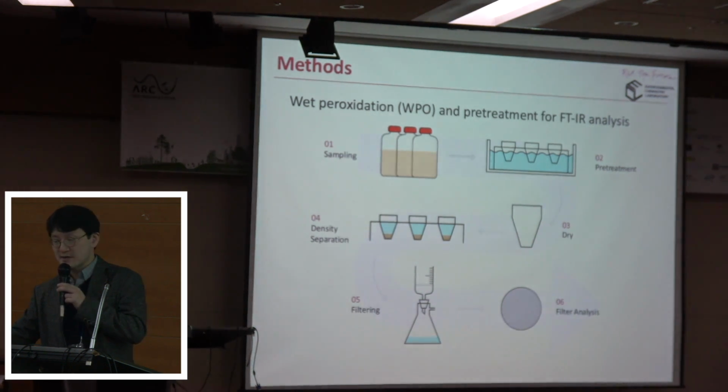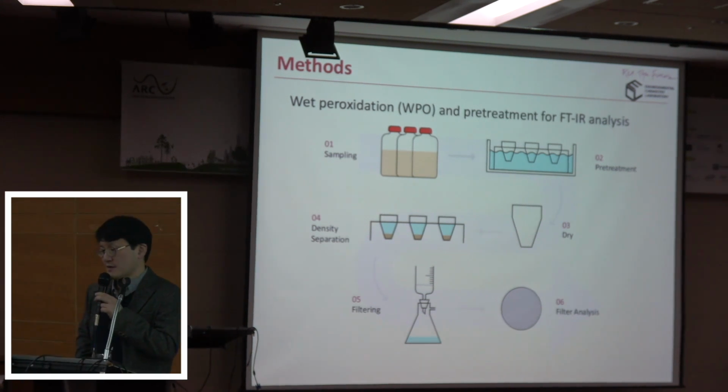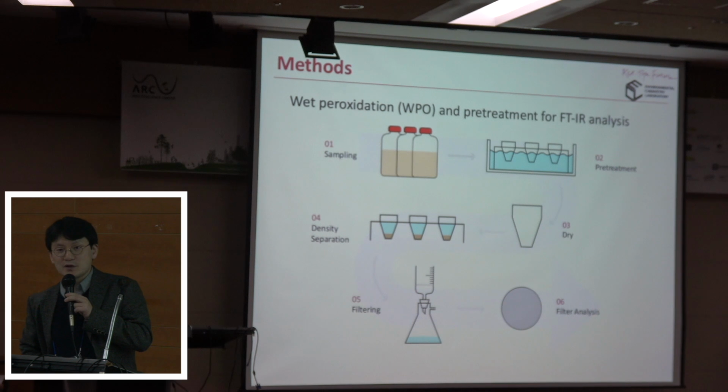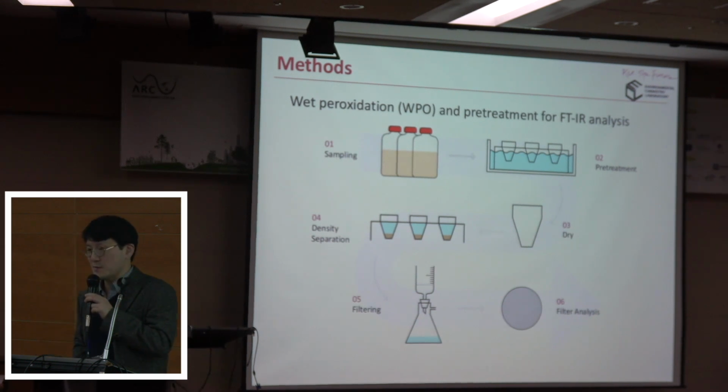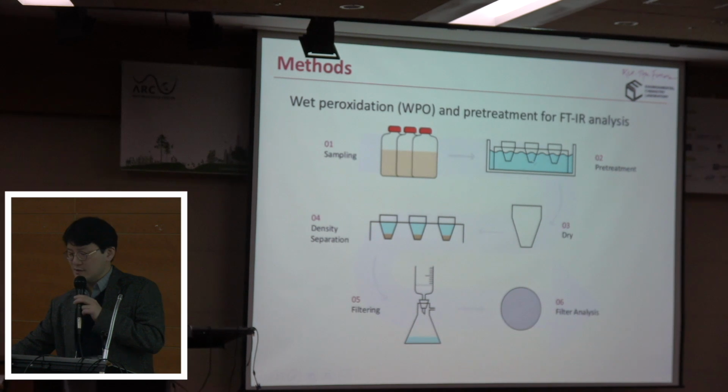The method has been reviewed in many earlier studies, and is currently the most widely used method of isolating microplastic from environmental samples. Because of the large amount of organic matter in these samples, we need to remove natural organic matter from synthetic particles. Typically, the hydrogen peroxide oxidation method is used, and the sampled water was pre-treated using H2O2.